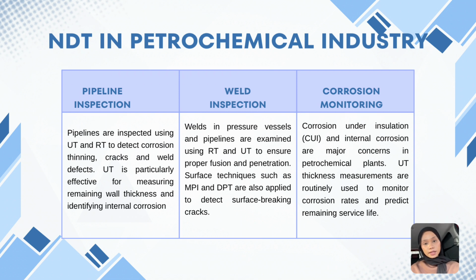In petrochemical plants, corrosion under insulation and internal corrosion are major concerns. Ultrasonic thickness measurements are routinely carried out to monitor the corrosion rates and to help predict the remaining service life of equipment, and this will help to prevent unexpected failures and also to ensure plant safety.